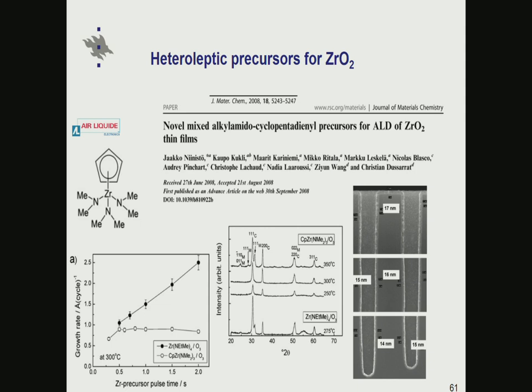And this is, well, we saw this curve already. At 300 centigrades, there is no saturation with the alkyl amide, but with the CP heteroleptic compound, there is saturation. And the saturation is now to a higher level than in the previous CP compound, so it's about 1 angstrom per cycle level. And with very nice step coverage in aspect ratios of, I think these were 80:1 or 60:1.